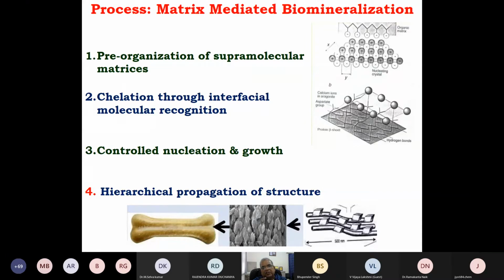cations, so cations or anions, depending on the polarity, they will go and attach with a secondary bond to the functional group. Depending upon the ionic condition of the functional group, the cations or the anions will go to the positive functional group or the negative functional group depending on the polarity. But they will reach the right site, they will not go randomly, right? And then under the optimum condition, you will have controlled nucleation, right?